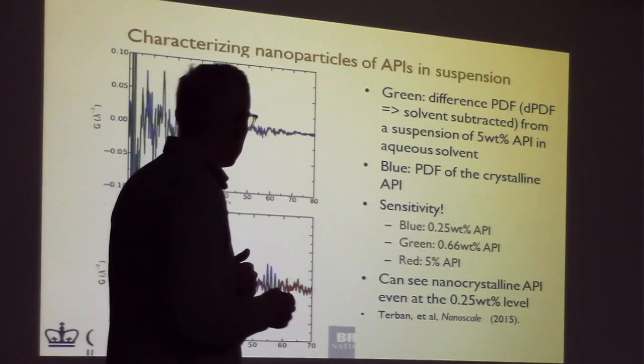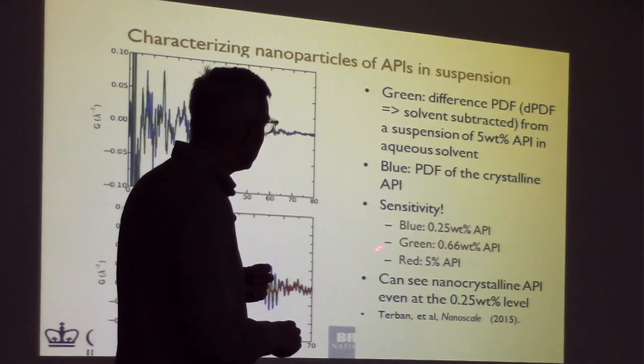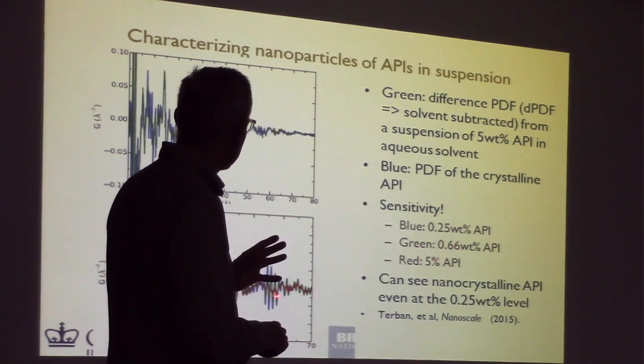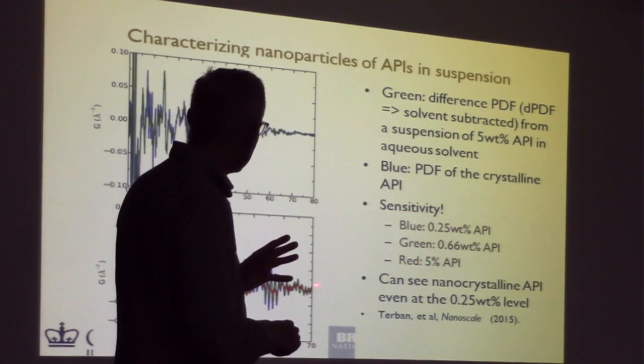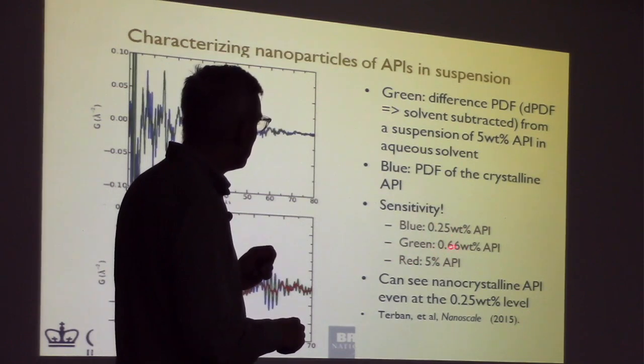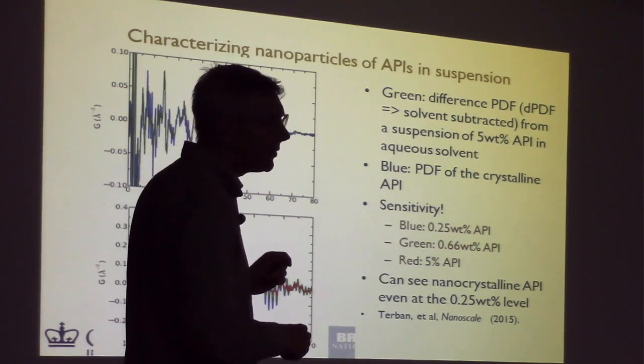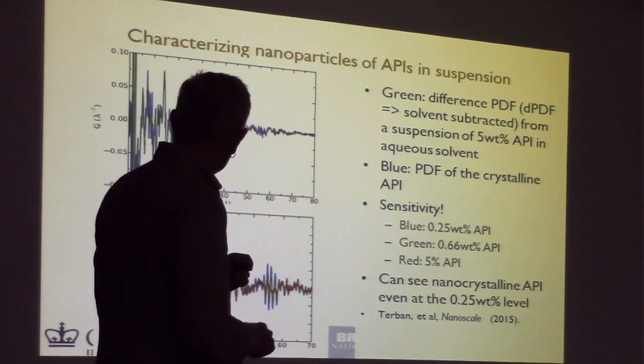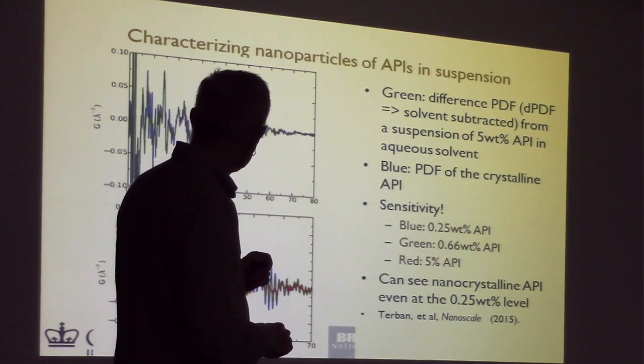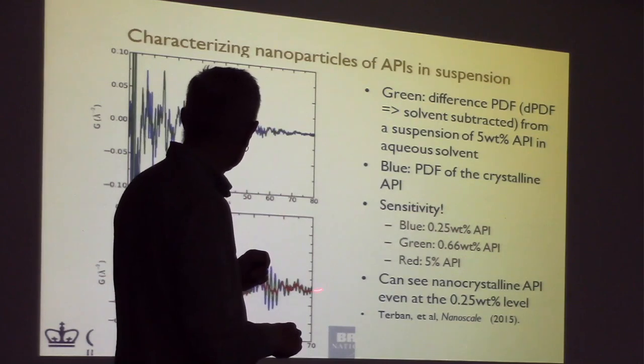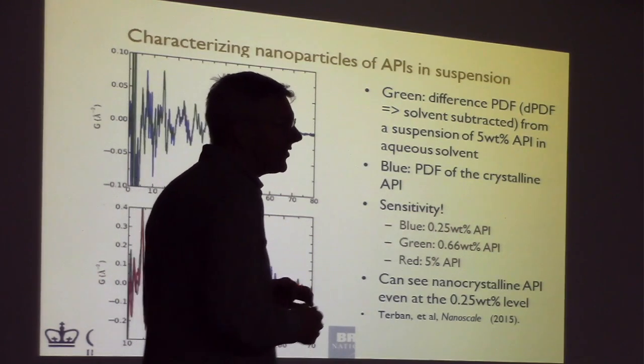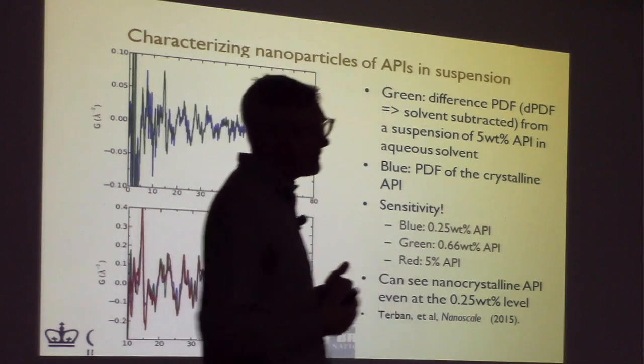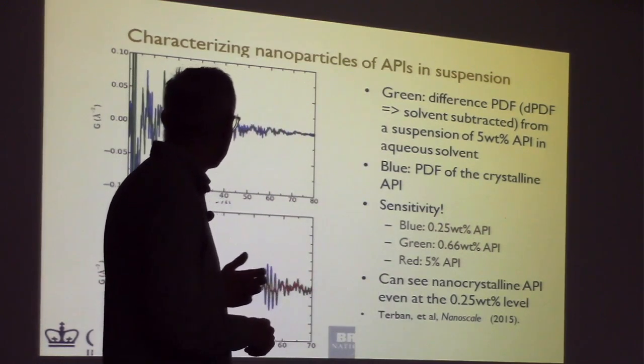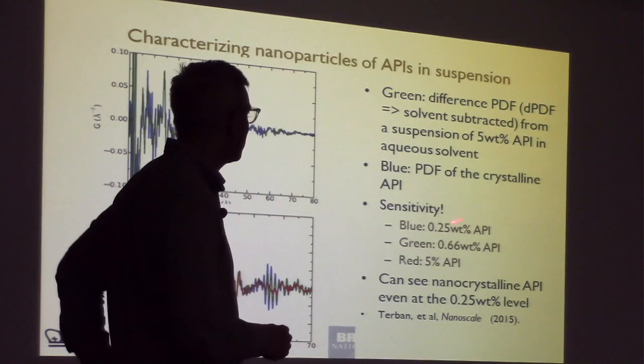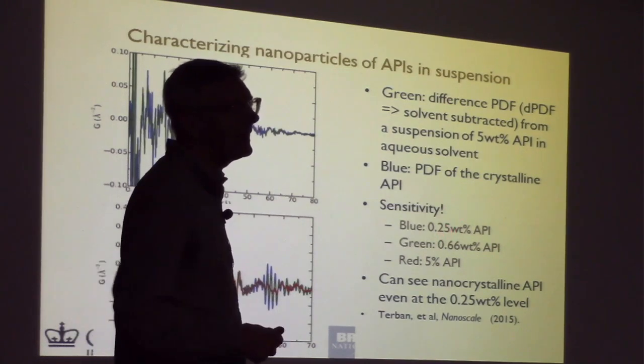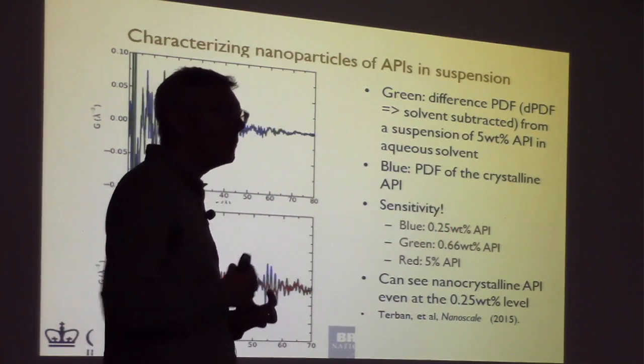we're seeing it. But then we went to the samples that he had brought that were the regular ones. So the red one is the 5 weight percent API. Then the green one is 0.66 weight percent, and the blue is 0.25 weight percent. And you can see that although the signal is getting much more noisy, we're definitely recovering the signal down here. So this showed us that using these new computational methods and the best quality data, we can actually get extremely high sensitivity. So it's 0.25 weight percent, and it's an organic in water.